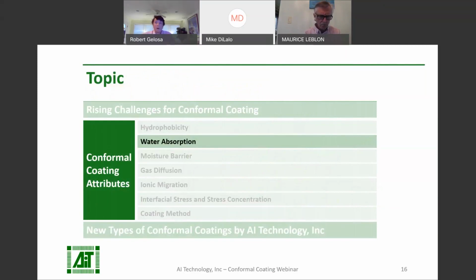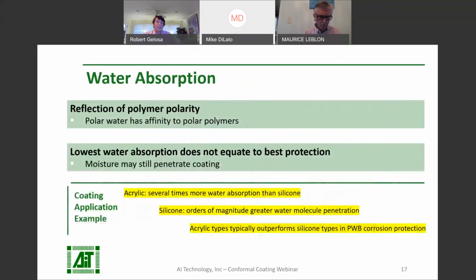Next, let's take a look at water absorption. Low water absorption is an important factor. We don't want a lot of water sitting in our coating, easily accessing the interface between the coating and the board. That said, low water absorption alone is not enough to provide the best protection. So acrylic and silicone are used by many people in the electronics industry. They're well known, so let's compare. Generally, acrylics absorb much more water than silicones. But at the end of the day, acrylics still typically provide better protection than silicones. It's because despite being more hydrophobic and having lower water absorption, silicone has a much greater moisture permeability than acrylic.